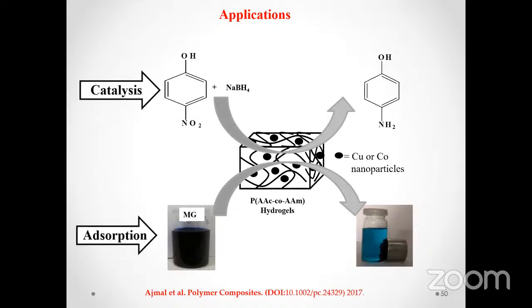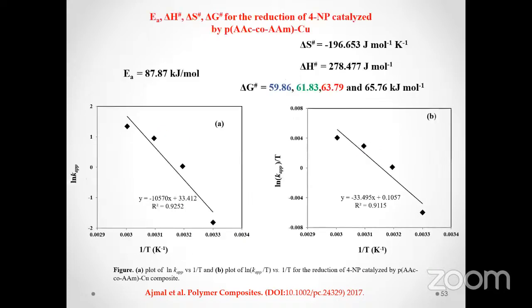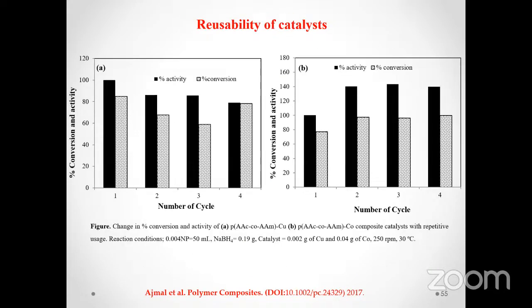These details I have already discussed. Again, the same parameters have been calculated. Recycling was also observed in this case. And interestingly, a slight increase in the catalytic activity was observed after the first cycle when we studied the recycling. This increase in the catalytic activity can be observed due to the elimination of some impurities which can be adsorbed on the catalytically active sites during their synthesis. There might be some other reasons.